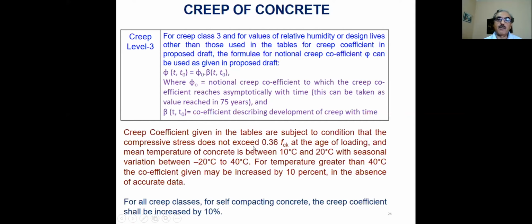However, these coefficients are applicable when the compressive stress does not exceed 0.36 FCK at the age of loading, and mean temperatures are in the range of -20 to 40 degrees centigrade. If temperature increases, the creep coefficients have to be multiplied with the coefficient.